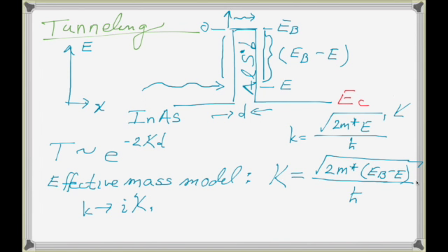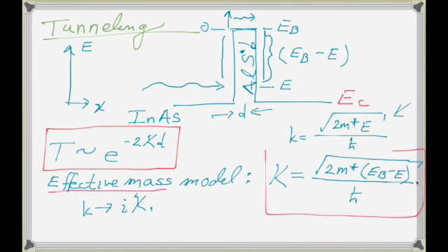And in the WKB approximation, this transmission coefficient is just roughly e to the negative 2 kappa d, where kappa in the effective mass in your parabolic model would just be given by this. It's sort of just turning your dispersion upside down, measuring from the top of the barrier how deep you are from the top of the barrier in terms of the energy argument that goes under the square root.